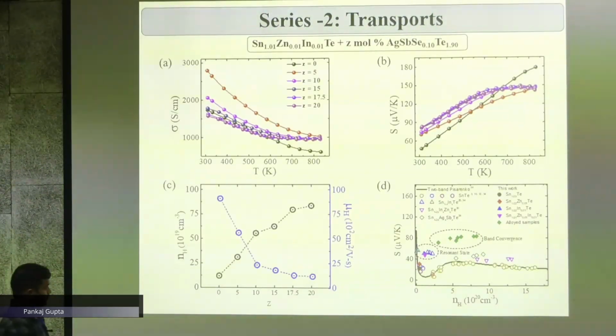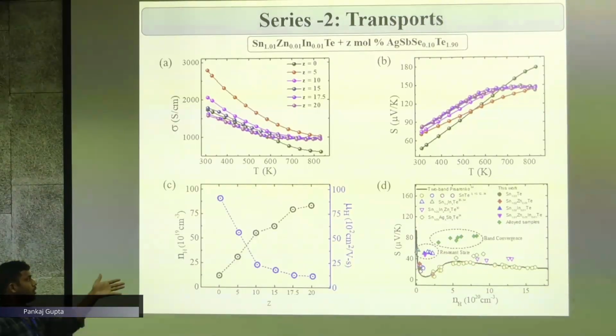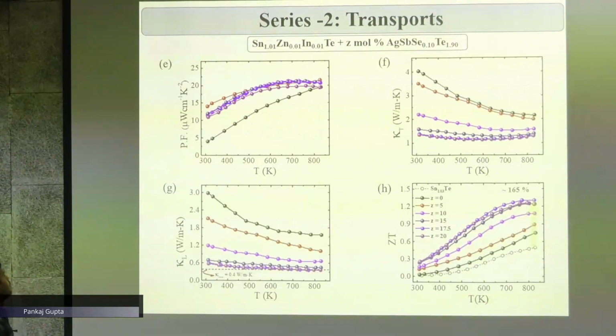And to look more into detail at why, at the same time, carrier concentration is increasing but Seebeck is also increasing, we plotted the Pisarenko plot, that is the theoretically accepted plot, and we found that the Seebeck value is coming out higher, meaning there is some band convergence signature and a resonant state signature that is playing a role in increasing the Seebeck values.